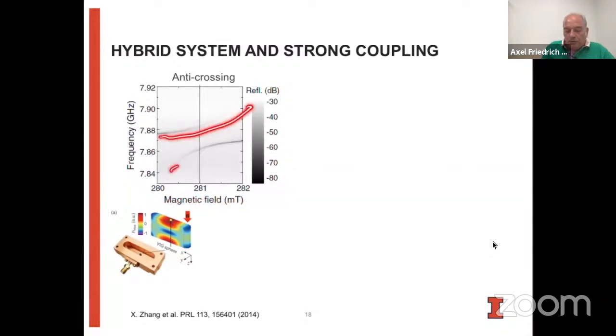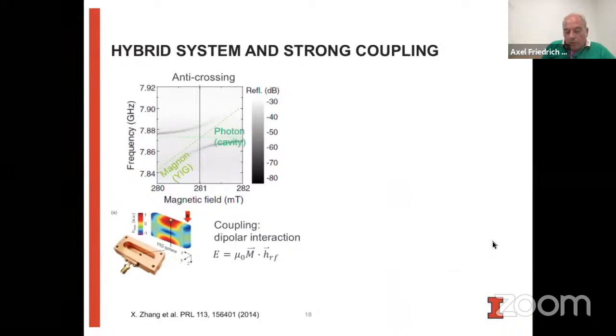And you see these two modes that are split with each other. So what they represent is a combination of two modes. One is a photon mode, which really is just a photon mode of the cavity, which is independent of the magnetic field. And the other one is the magnon mode of the yttrium iron garnet, which of course shifts with the applied magnetic field. And it shifts upwards as you increase the magnetic field. And due to the interaction, you get a splitting at the point where these two modes cross. And the magnitude of this splitting gives you a direct measurement of the coupling. And the coupling in this case is just how the magnetization of the YIG sphere couples to the microwave resonance field of the resonator.